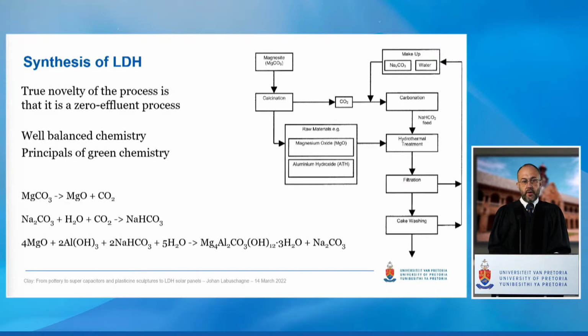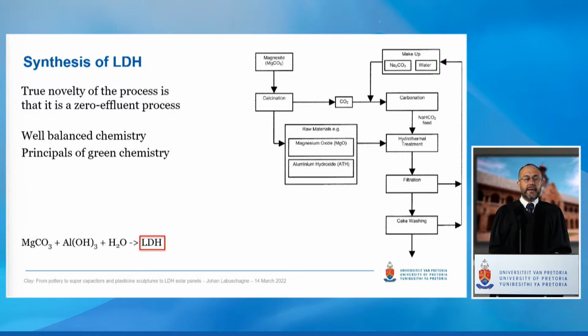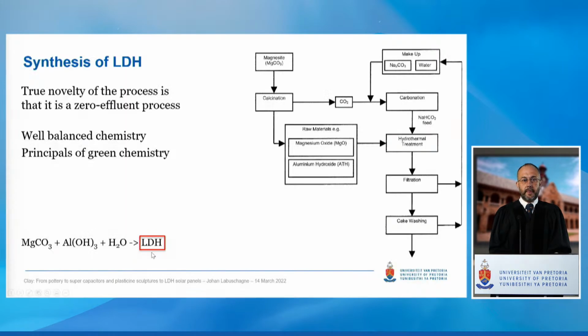The novelty in this process was in the second reaction. If you look at this, you can see that we could recycle the sodium bicarbonate that formed during the process back into the system. We could then use the CO2 from the initial calcination reaction to regenerate the sodium bicarbonate. In this way, having the sodium bicarbonate completely acting as a catalyst, although it strictly is not a catalyst. In the end, we end up with a reaction where we start with run-of-mine magnesium carbonate, aluminium hydroxide, water, and we formed the LDH. This was quite novel in the early 2000s.